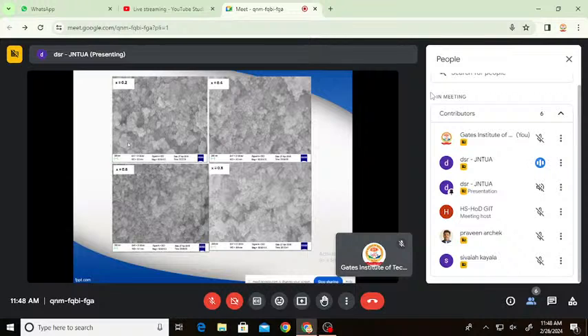Coming to this FESEM analysis, see from the images of the FESEM, it is observed that all compositions possess inhomogeneous distribution of grains. Besides that, distinct stone shaped particles, here we can see somewhat stone shaped particles, were noticed for x equal to 0.2 and 0.4 compositions. Spear like grains were found for 0.6 composition. For 0.8 composition, nanofibers were formed.